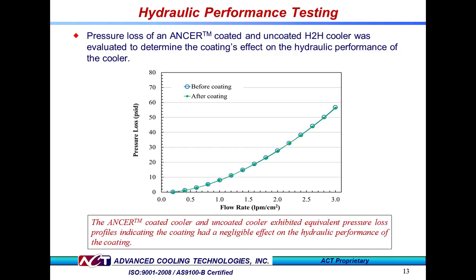Again, we show results for an uncoated and then ANCER-coated sample at 0 hours of life. Here we are measuring hydraulic performance, the pressure loss across the microchannel coolers as a function of flow rate. This is a test to determine if the ANCER coating affects the flow of the highly engineered microchannel cooler internal features. Hydraulic performance can change by either restricting or expanding flow channel dimensions. Again, we see that before and after coating results are identical, and we conclude that the coating has not affected the design flow path of the MCC.